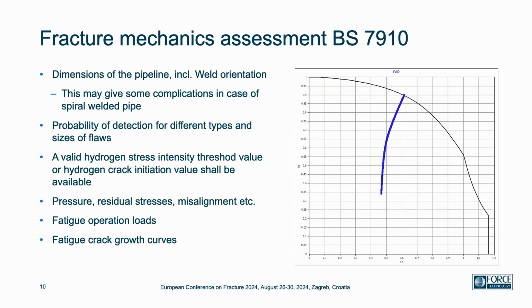And to do these assessments, we of course need the dimensions of the pipelines, including the weld orientation. And this weld orientation actually gives some complications in the case of a spiral welded pipe. We need to know the probability of detection for different types of sizes and flaws. A valid hydrogen stress intensity threshold value or hydrogen crack initiation value shall be available. We need to know the pressure, the residual stresses, misalignment, and so on, fatigue operation loads, and the fatigue crack growth rates. And then we can determine the fatigue crack growth according to the failure assessment diagram. And when it reaches the curve, then we reach an unsafe or a critical crack size.